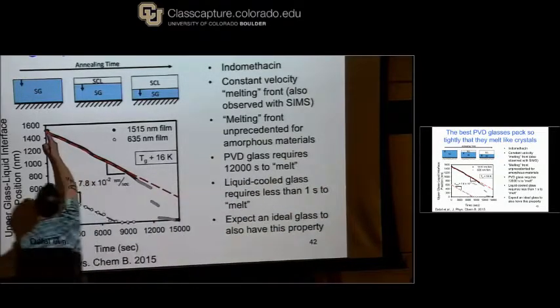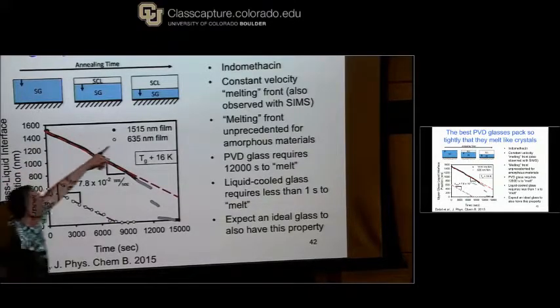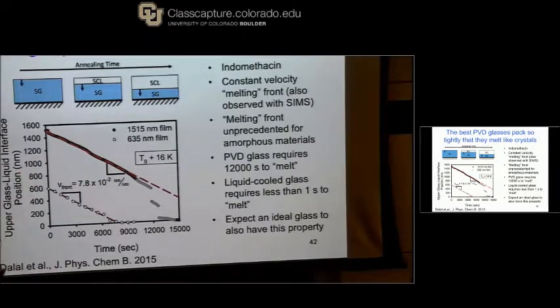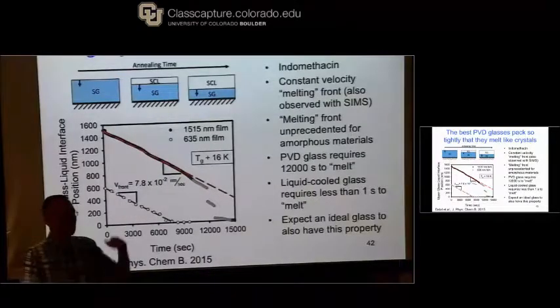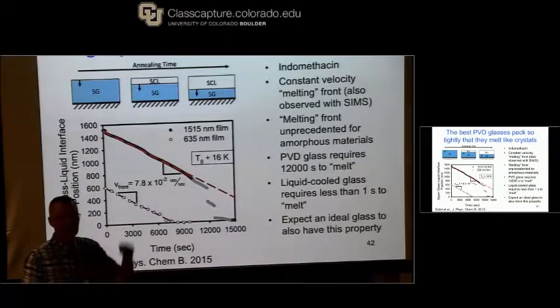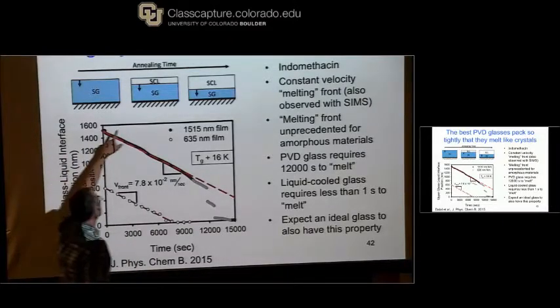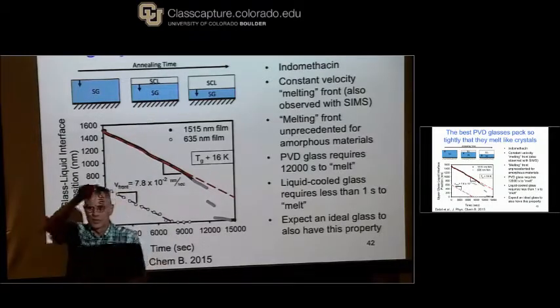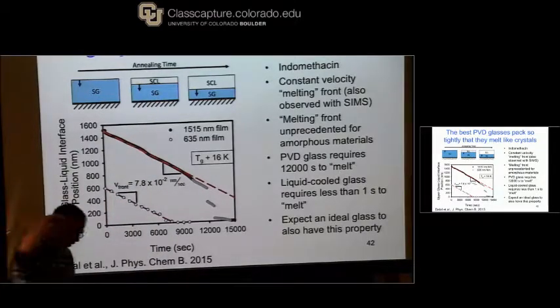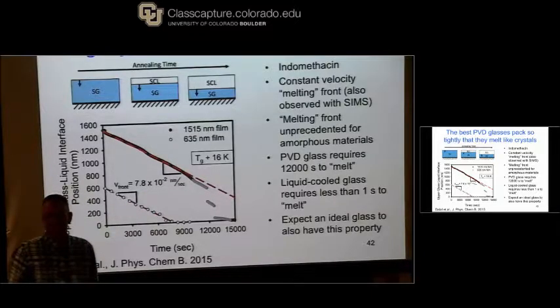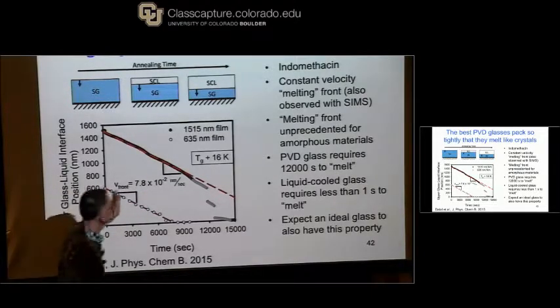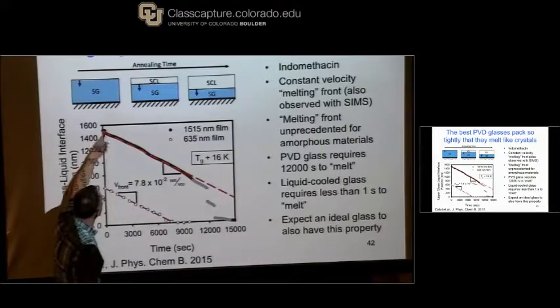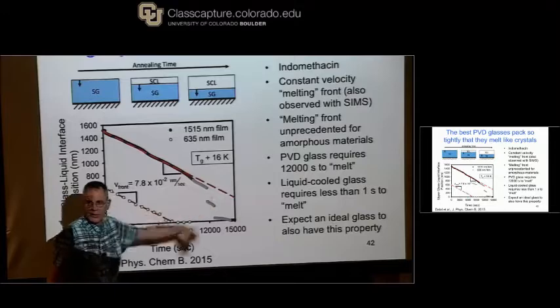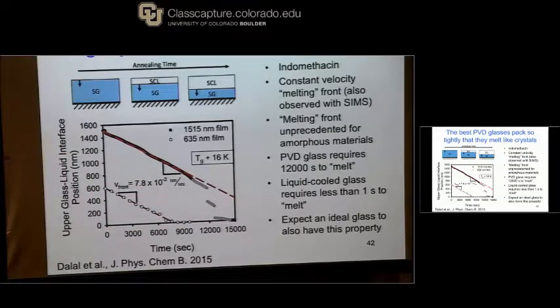So here we vapor deposited a film that's 1,500 nanometers thick. We put it on the ellipsometer. Now this time we use a good model for the ellipsometry, one that knows that the material might not be homogeneous. And what the model tells us is that there's an interface inside the sample with a discontinuity in the index of refraction, and some light is reflected off of that interface. We can do this experiment in real time. We can track the position of the interface as it moves down through the sample. And that interface is the highly stable glass transforming into the supercooled liquid.